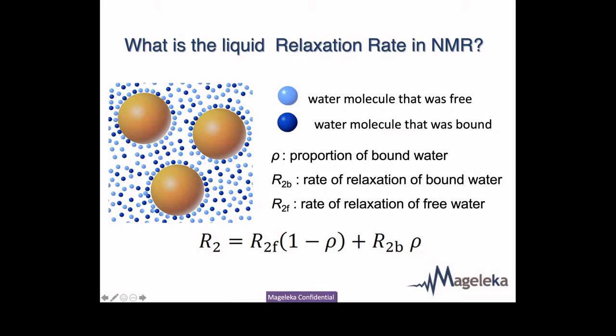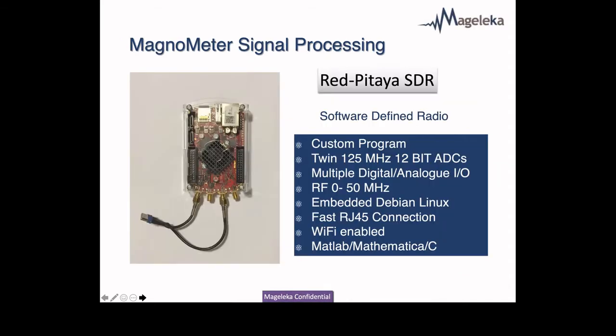And if those of you like equations, here's an equation which tells you the average relaxation time. This is actually the relaxation rate. It's 1 over the relaxation time. It depends on the number of free water molecules and the number of bound water molecules. And so by measuring this number, the first thing we can tell you is how many bound water molecules there are. That is directly proportional to the available surface area of the particles. So immediately we have a very simple way of measuring the available surface area, or the weighted surface area, in a dispersion. And this is the key to virtually all the experiments that we're going to show you today.